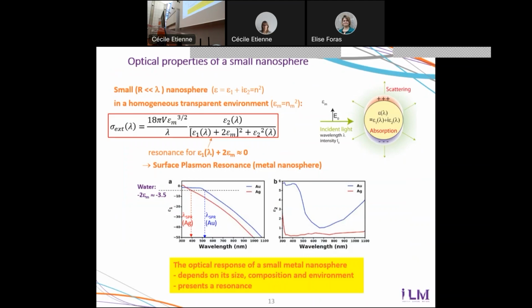A second key message, so here one has to look at this denominator. So usually in the denominator, the dominant term is the first one. But actually, this first term for metal nanoparticles is something that can be zero. So if you have a small denominator, it means that the extinction of the particle will be much larger. The particle will very strongly absorb and scatter light. So it's called the surface plasmon resonance of metal nanoparticles.